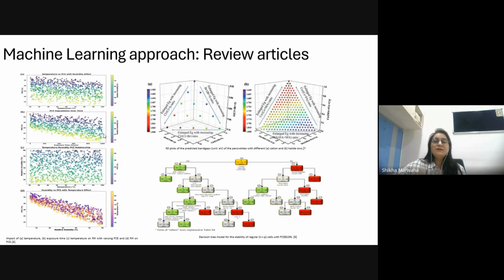Here one material was taken, and this particular set was studied at different temperatures and humidity to see how it behaves. Secondly, it was studied for different exposure times. Then it was taken by combining temperature and RH while varying the power conversion efficiency. And the third is RH on power conversion efficiency. By RH, I mean relative humidity.